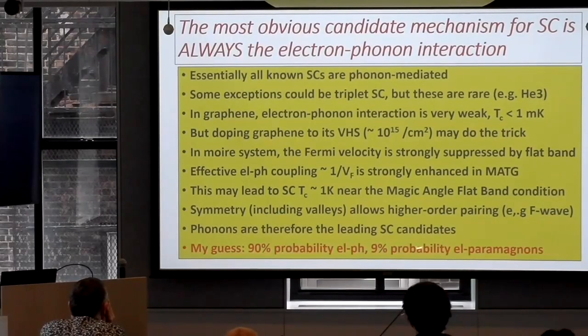So my current belief is that there are some situations, in particular Bernal bilayer graphene, where it is probably electron-paramagnon, but the rest are electron-phonon. I'm not very happy with that. If two mechanisms come in, it's possible others come in also. So the question is open. I want to distinguish between what I believe and what I can show. What I believe is almost all electron-phonon. But what we can show is definitely there is one example, Bernal bilayer graphene, where electron-phonon doesn't explain the superconductivity, but electron-paramagnon does. So there is still a lot to do.